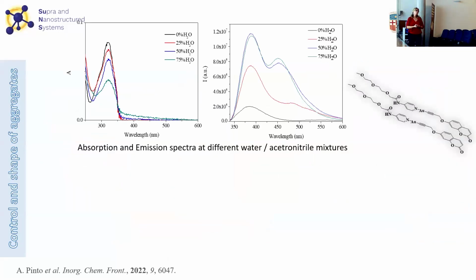So how can we perform these self-assembly experiments? Well, what we do is prepare a batch of different samples, exactly with the same concentration, but modifying the solvents that are present. So we work with two solvents. One of the solvents we call the good solvent, where the molecule is completely solubilized. And another one is what we call a bad solvent, the solvent that is promoting the aggregation process. So in these cases, we work with acetonitrile as good solvent and water as bad solvent.